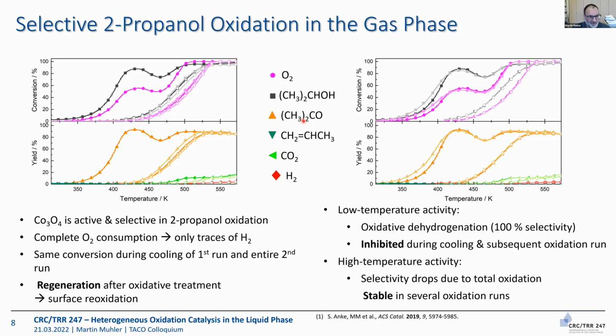Acetone plus water. So we have a low temperature channel, then we are up at the highest temperature, then we cool down again. And when we cool down again, then you see immediately, we have lost this low temperature channel. The high temperature channel is still there. And when we heat up again, then we are always here. So that means this low temperature channel is only present once, directly after heating in oxygen.